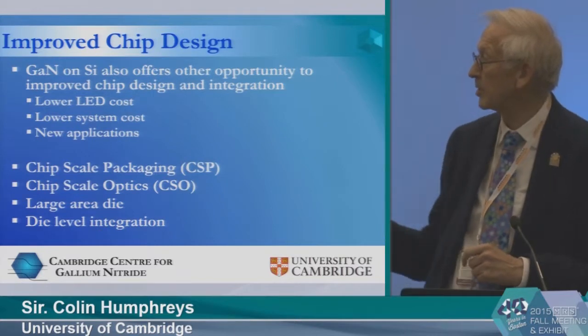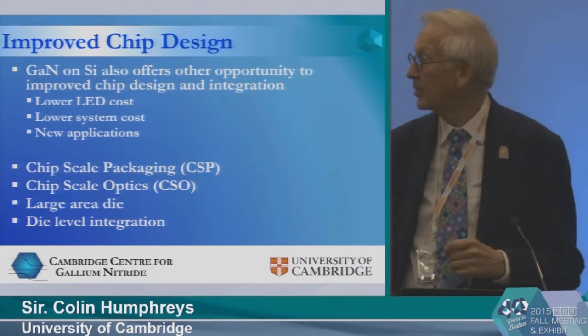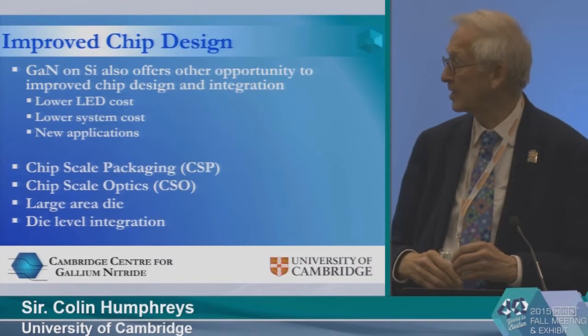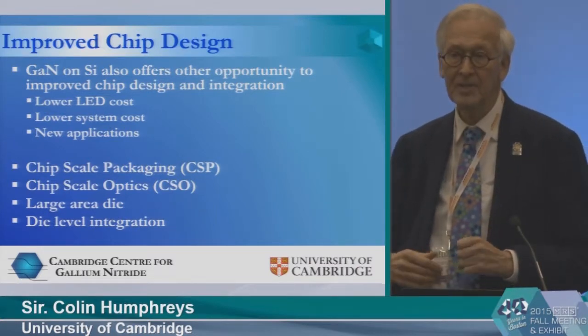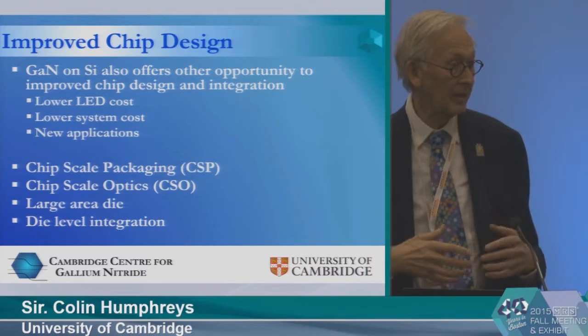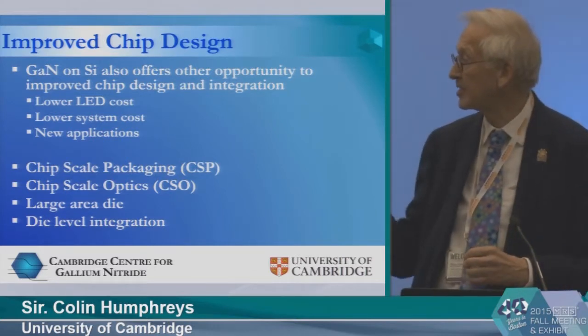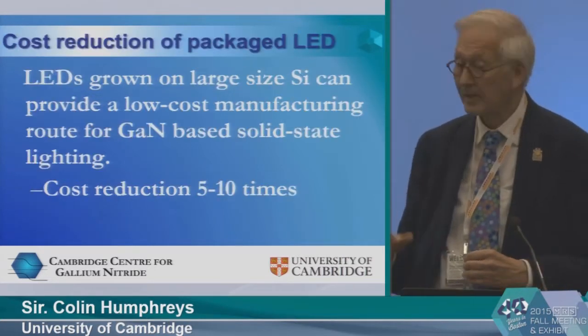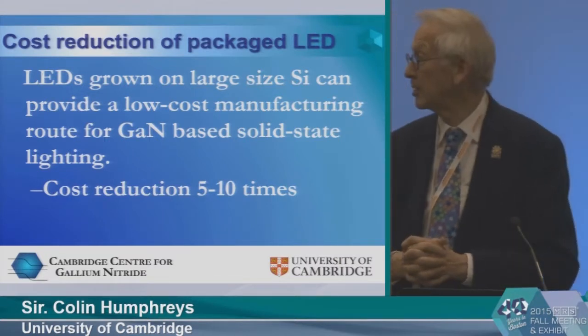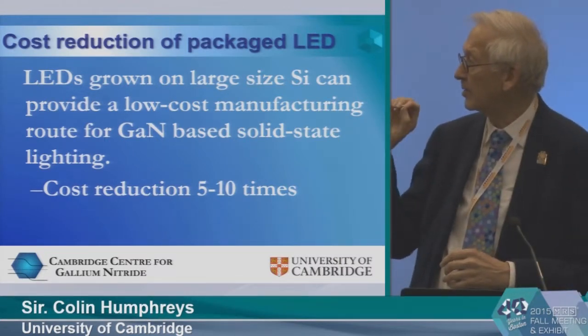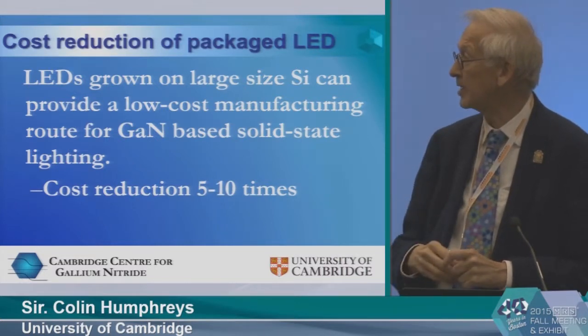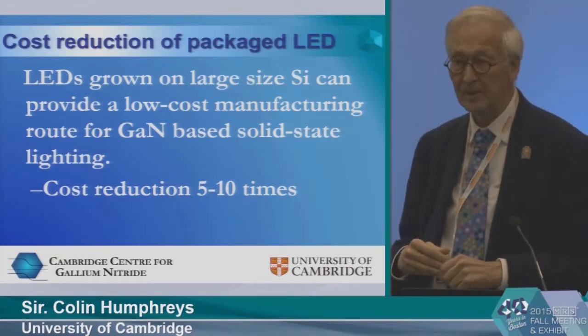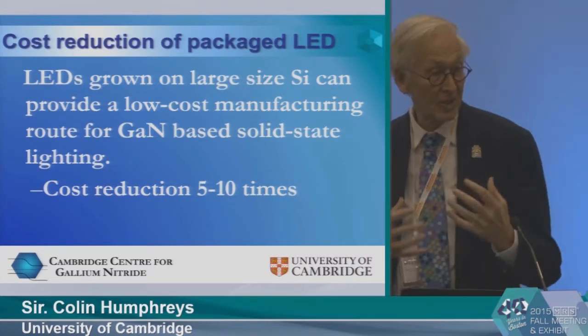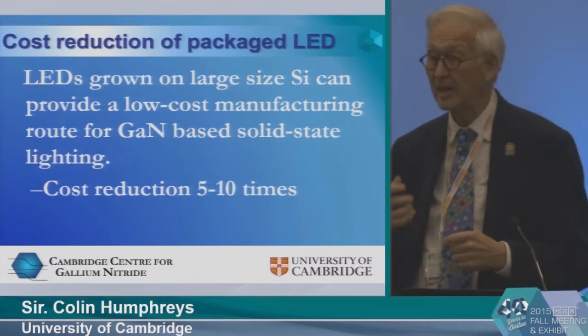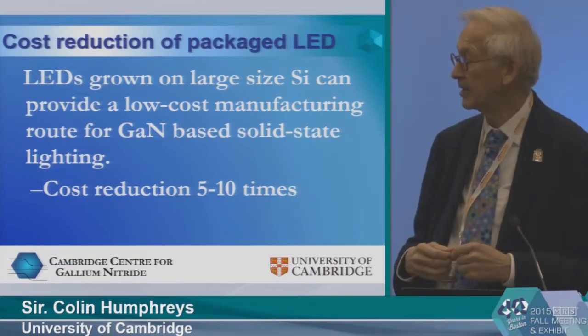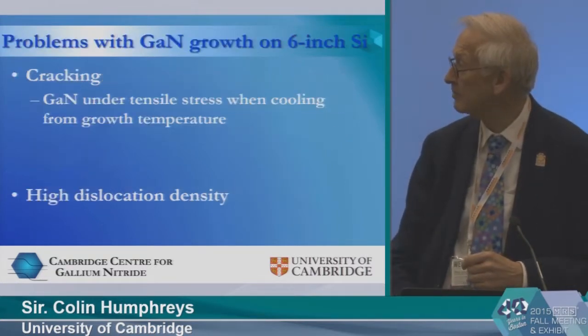Now, I don't have time to deal with that, but just to say, if you grow on 6-inch silicon, you can then do chip-scale packaging rather easily and chip-scale optics. And this hasn't yet been applied in the gallium nitride area, but it's starting to be applied, and these will bring significant savings. And the company which is exploiting that technology, Plessey, which I mentioned, they reckon that the total cost reduction of a packaged LED grown on large area silicon is typically 5 to 10 times. So these are just the sort of large cost savings you need if these devices are going to be really cheap and compete with compact fluorescent lamps.